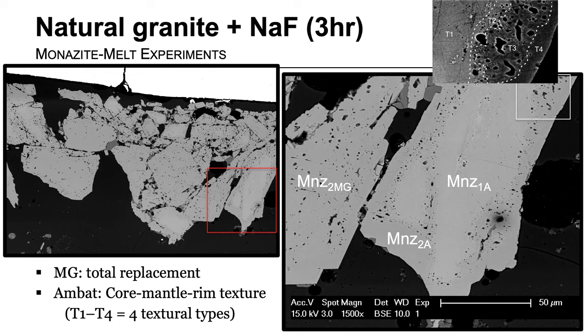We interpreted 4 textural types shown in the upper right. Textural type 1 is the core of the grain. It represents the original mineral standard that we put in. It then goes through 2 porous zones, T2 and T3, to a textural type 4, which are these relatively inclusion poor rims of the grains.